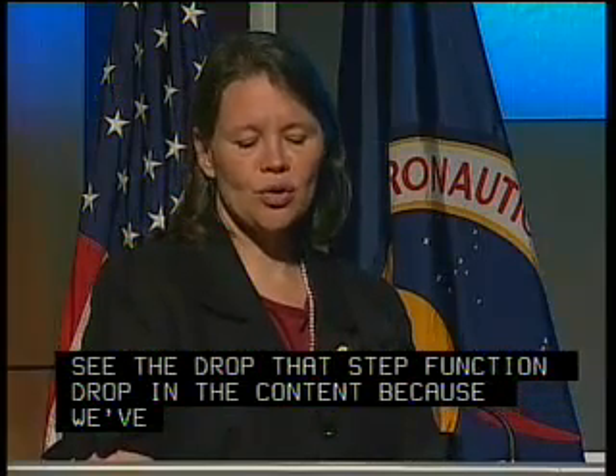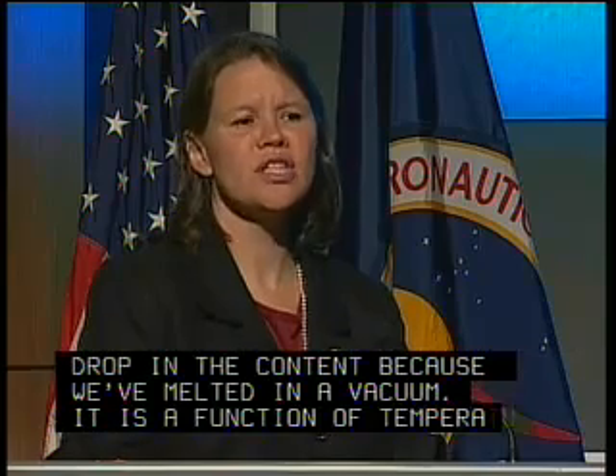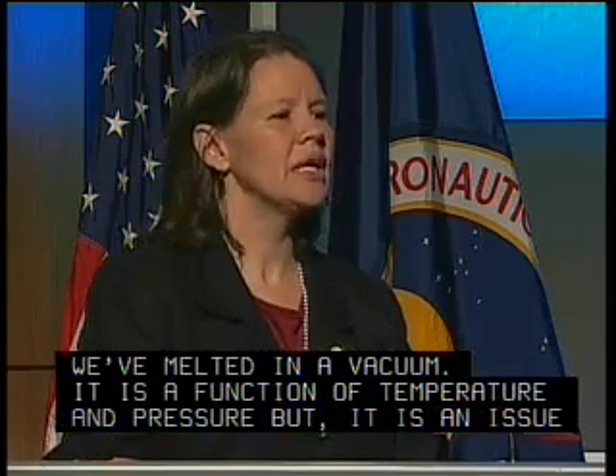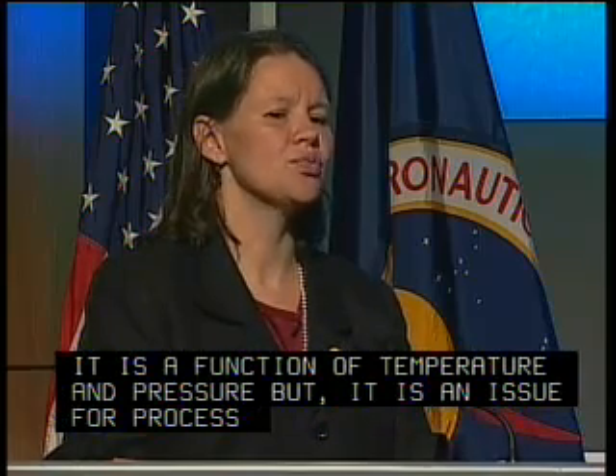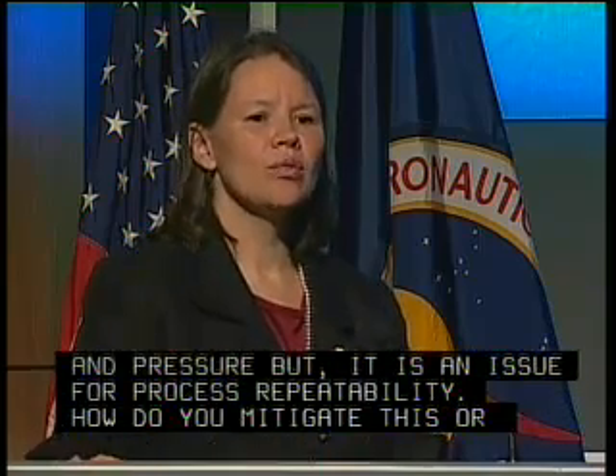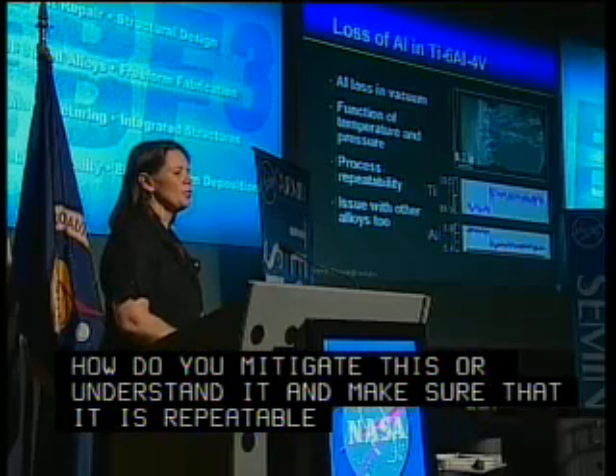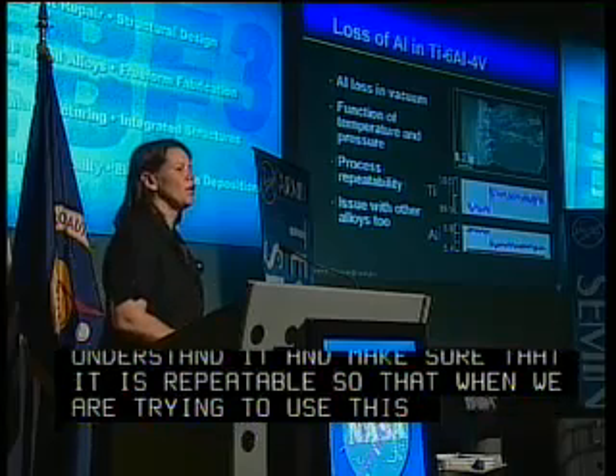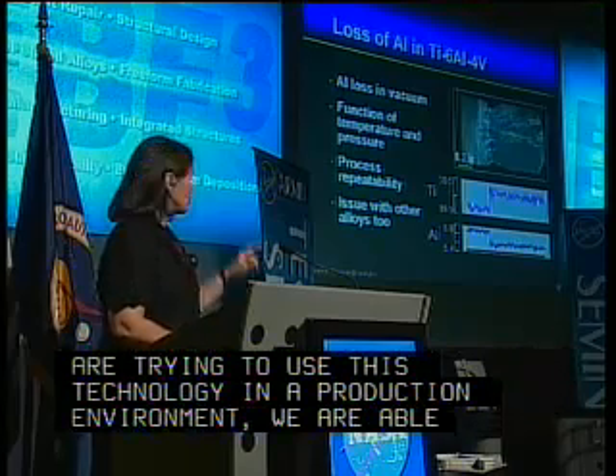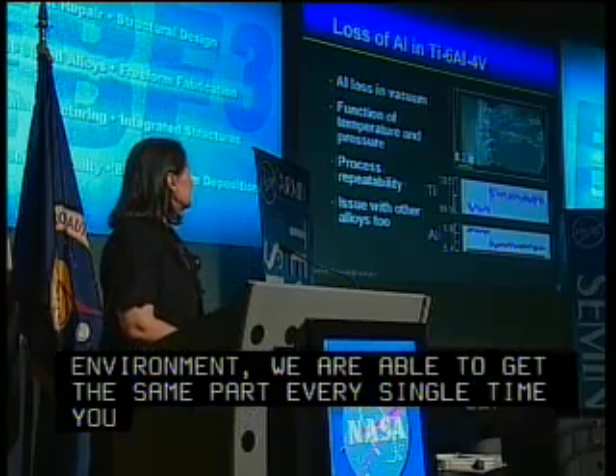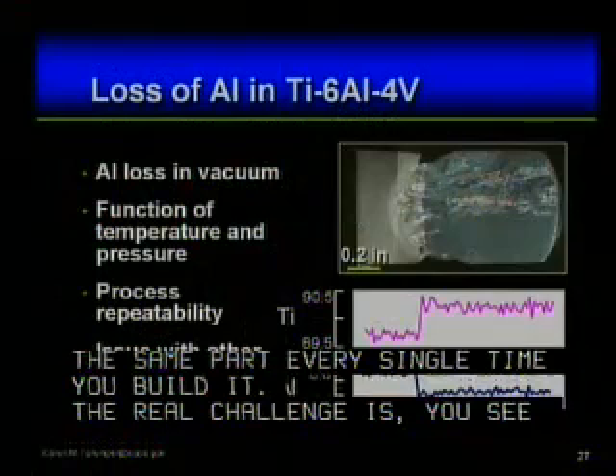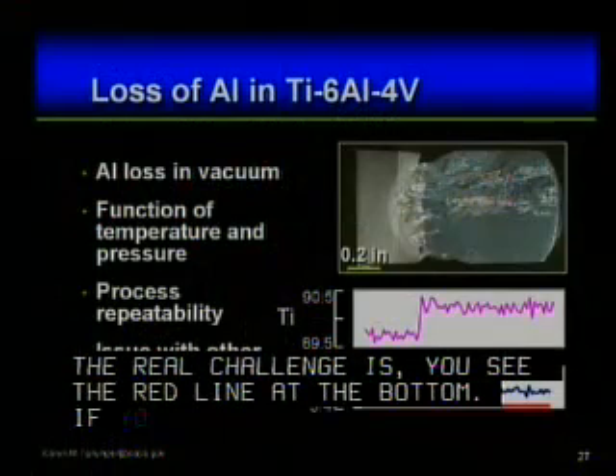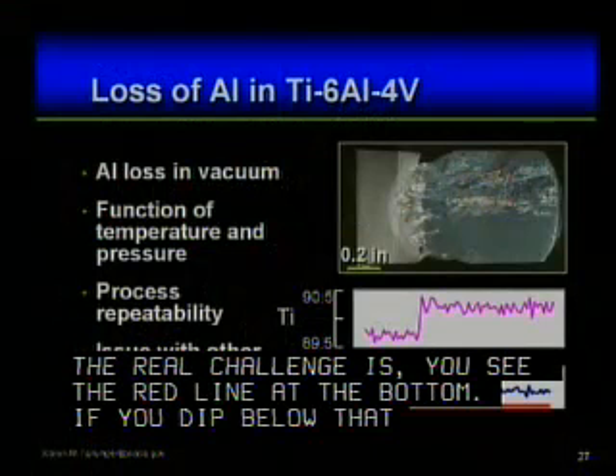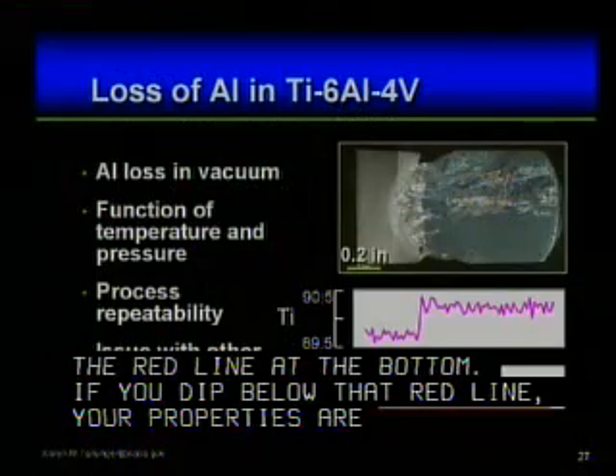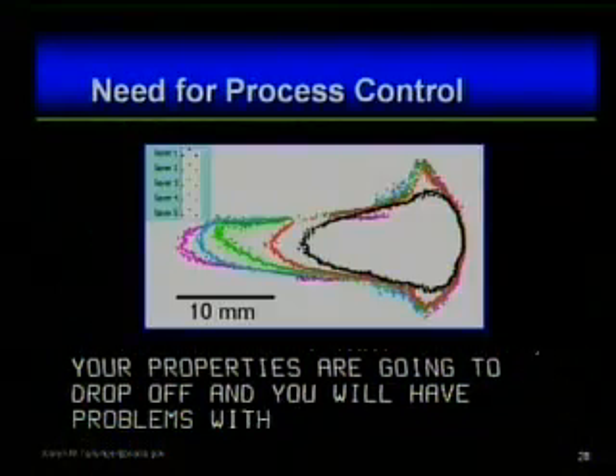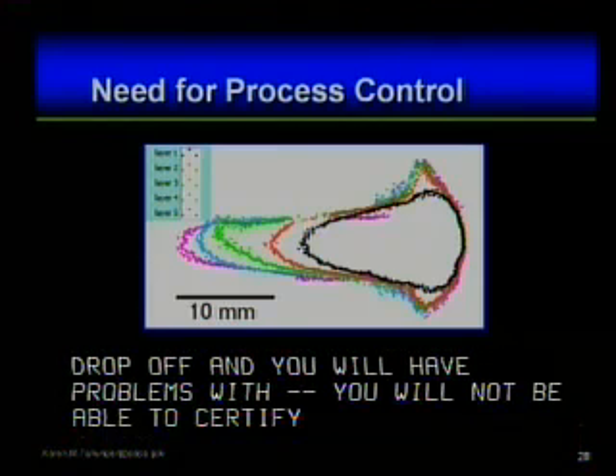It's a function of temperature and pressure, but it's an issue for process repeatability. So this is one area that we're looking closely at: how do you mitigate this, or how do you at least understand it and make sure that it's repeatable, so that when we are trying to use this technology in a production environment, we're able to get the same part every single time you build it. And the real challenge is, you see the red line at the bottom of the aluminum trace. If you dip below that red line, you are no longer within the Ti-6-4 chemistry bound. And that means your properties are going to drop off, and you're not going to be able to certify the process. Next slide, please.